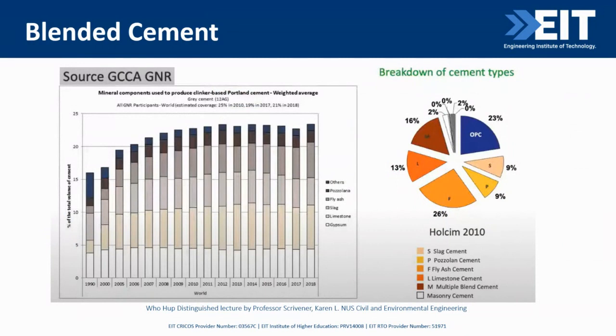Blended cement has been done for so many decades now. This chart on the left shows the figures for the substitution rates from the Global Cement and Concrete Association. We can see that the overall level of substitution is actually below 25%. Apart from gypsum, the most used materials are limestone, slag, fly ash, pozzolans, and some other materials.